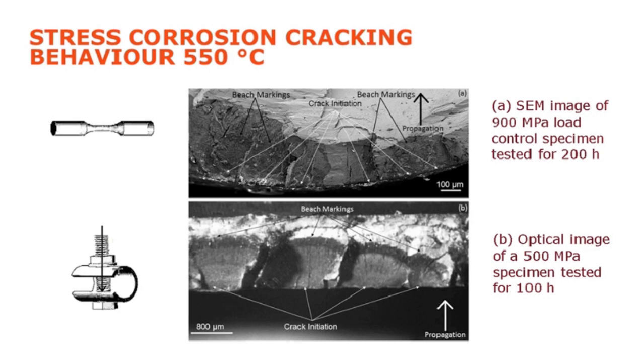Obviously it's very much dependent on the corrosion. So if you take away that corrosion, you obviously don't expect these materials to initiate and propagate cracks at these temperatures. It really is corrosion driven. The lower image is showing something similar, although it's an optical image rather than a scanning electron microscope image. And that's showing a similar thing on a C-ring at a slightly lower stress, 500 megapascals. But we can see again multiple crack initiation sites and environmental marking going on, showing the significance of the environment to this crack propagation.